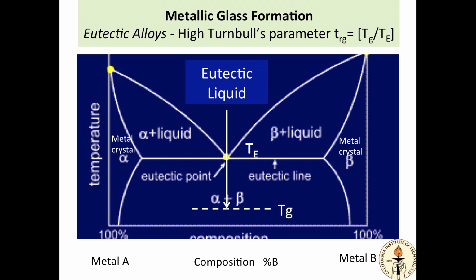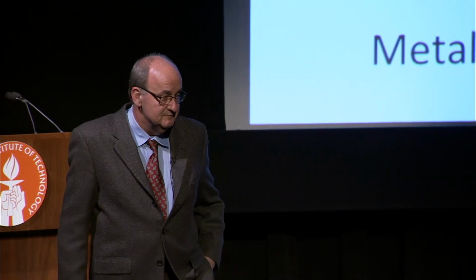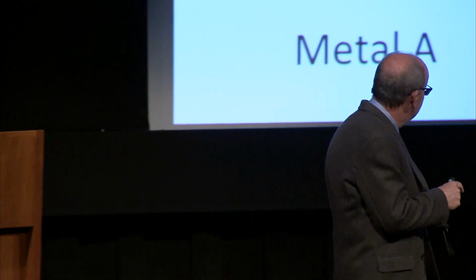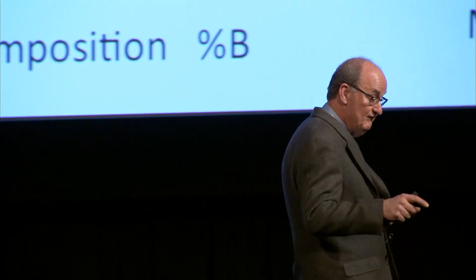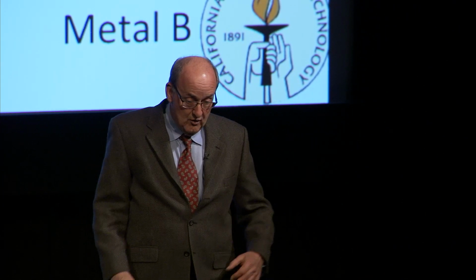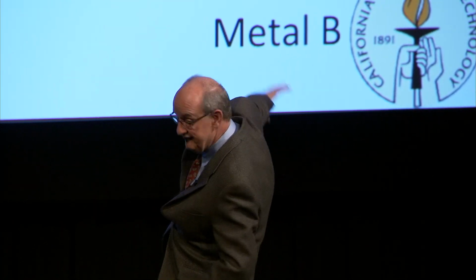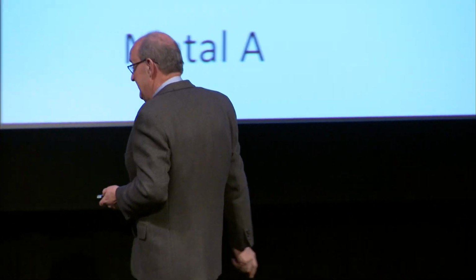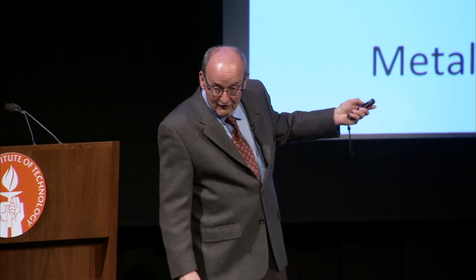Well, Turnbull told us we want the melting point, we want this glass transition, which is kind of down here, to have the highest ratio possible with the melting point. Obviously, when things melt together, you drop the melting point, the Turnbull parameter becomes favorable. The business of developing bulk metallic glasses is a business of putting 2, 3, 4, even 5 or 6 metals together to make a very deep eutectic, where we push the melting point very close to the glass transition, and that just squeezes the crystallization out. It works. With that idea, that's how Peker found the first bulk metallic glass, the ingots.